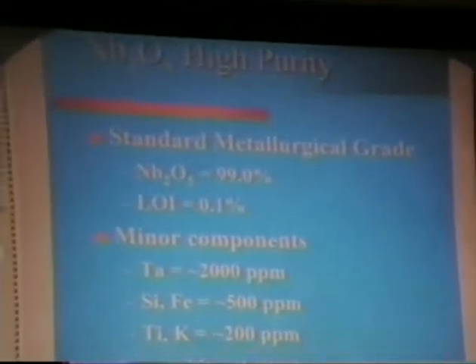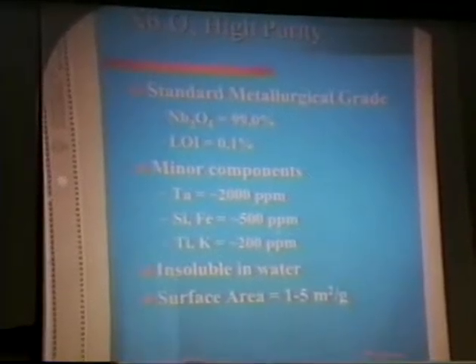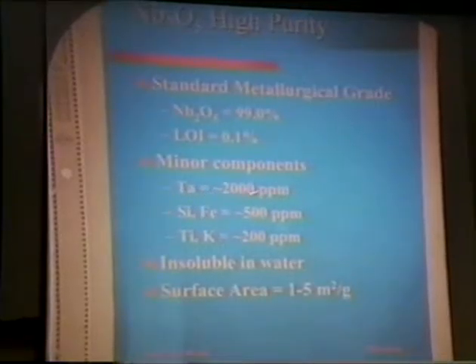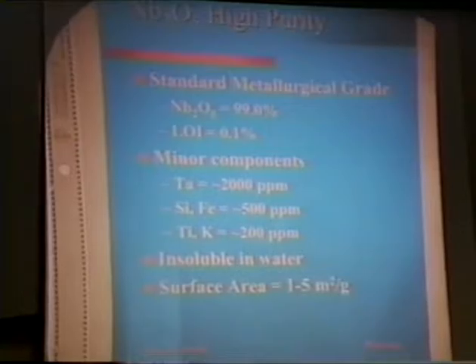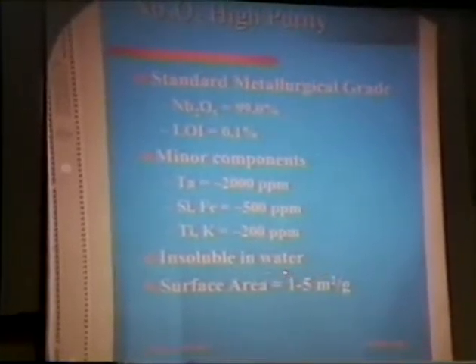The second material that I mentioned was actually the metallurgical grade material, high purity. And compared to a lot of metallurgical grade oxides, this is a high purity material. 99, minimum 99% Nb2O5. Some minimal loss on ignition, some water in there. Tantalum composition only about 2,000 ppm. Again, insoluble in water. There seems to be a lot of interest in this material as a support, even though the surface area is relatively low, only in the range of about 1 to 5, some variation in batch.